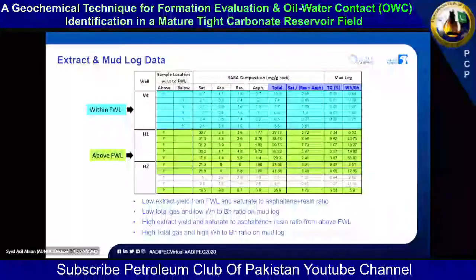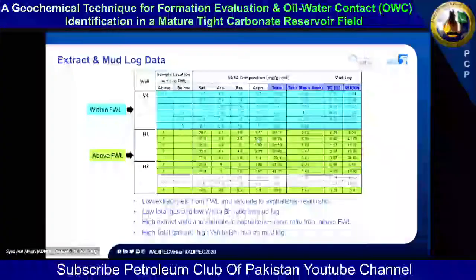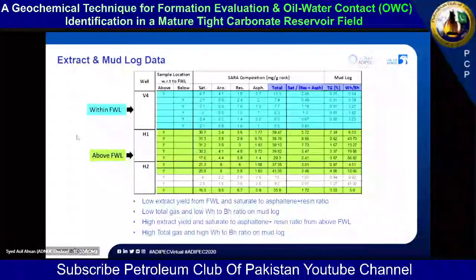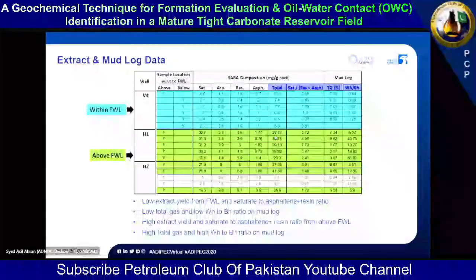So here it is in tabulated form, because in the previous slides the graphs were normalized to a certain value. So you were not able to appreciate the actual variation in the extract yield just by looking at those plots and figures shown in the previous slides. However, you can appreciate it here. I have taken samples just as an example, although I could have shown you all the wells, to show what you see in all those plots. So horizontal wells H1 and H2 have very high extract yield compared to the samples that came from within the free water level. Okay.